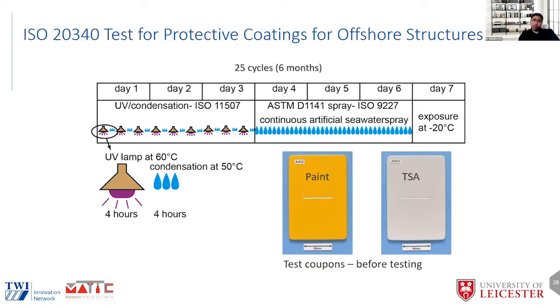Because this work was done a few years ago, we followed ISO 20340. This has now been replaced by ISO 12944, but the test procedure is still the same. So we looked at two different systems. One, a steel coupon with a paint layer. So again, this is a two-layer system. In case of TSA, it was just a TSA, thermal sprayed aluminium, layer of 300 microns thickness.